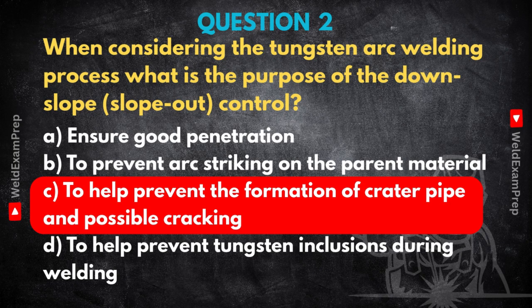These craters are really problematic, not just because they're a dip in the surface, but because that rapid solidification leaves them full of internal stress. So that combination, the geometry and the stress, makes them highly susceptible to cracking as the metal pulls itself apart, cooling. So by slowly ramping down the current, the downslope lets the pool cool and solidify more gently, more controlled. It effectively fills in that crater as it shrinks and minimizes those dangerous internal stresses. So it prevents both the pipe defect and the cracking that often comes with it.